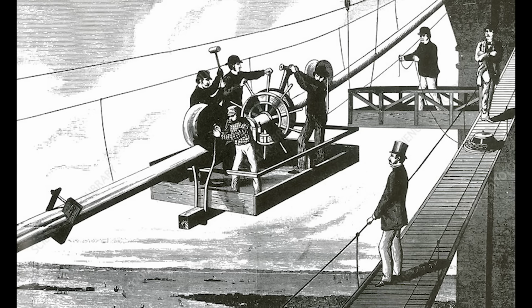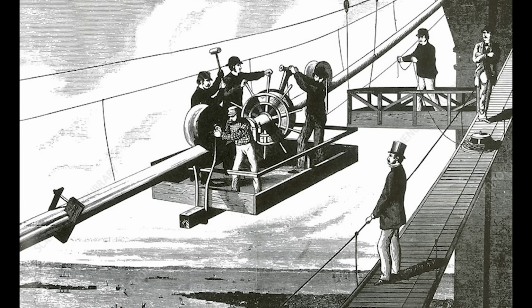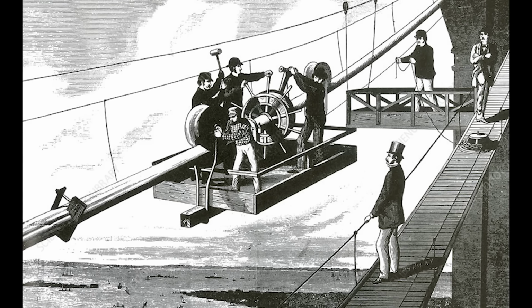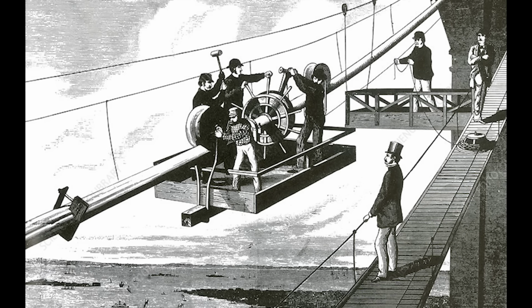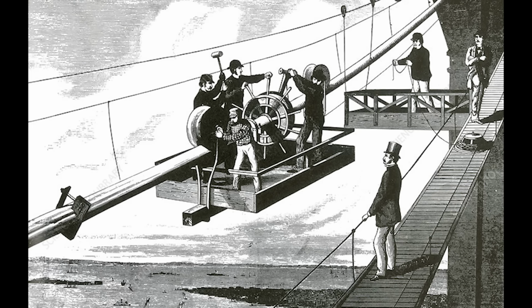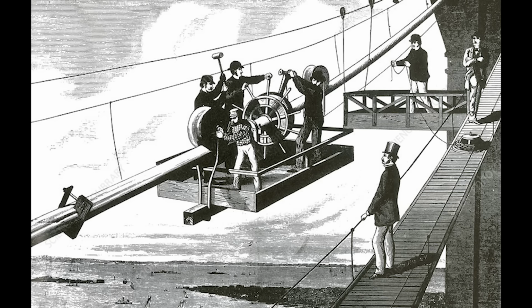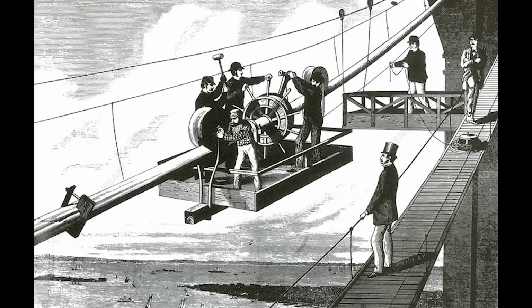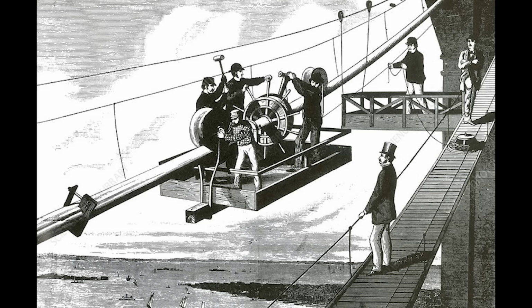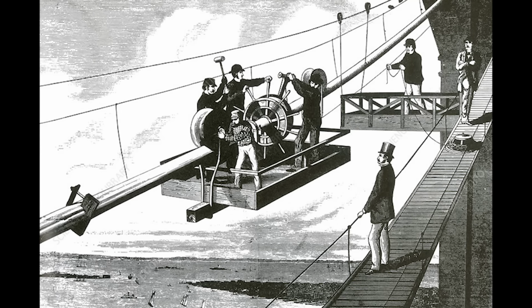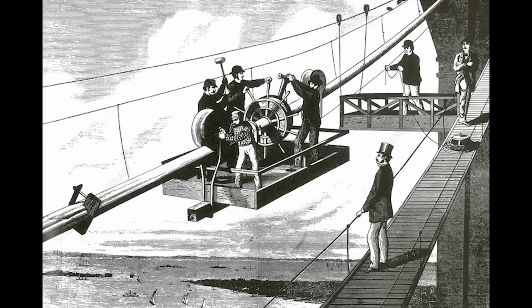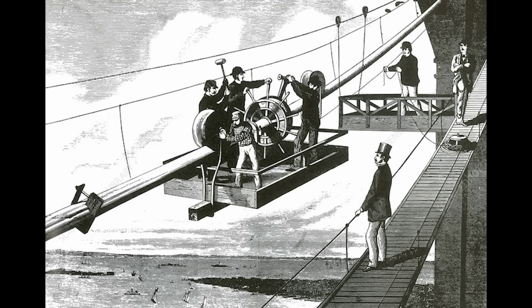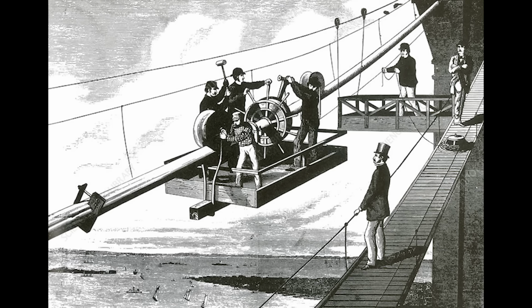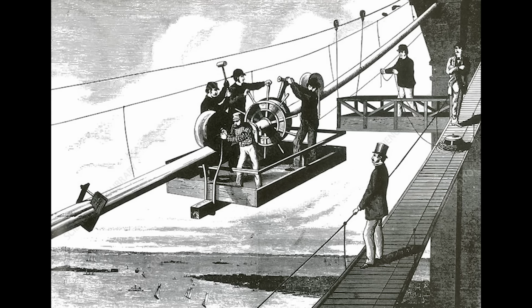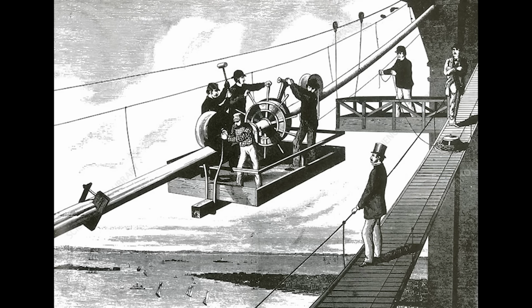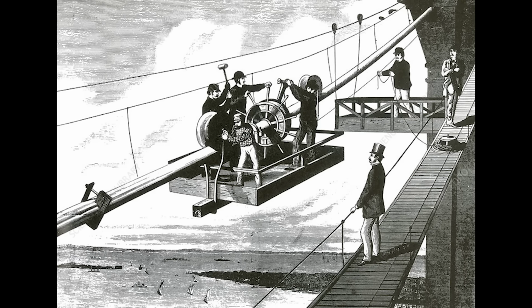The wire arrived at the Brooklyn yard in massive spools, each strand already bearing its zinc armor from the contractor's galvanizing works. Roebling examined the first delivery through his magnifying glass, noting the characteristic crystalline surface that indicated proper hot dip processing. The zinc hadn't been painted on or electroplated. It had been alloyed into the steel's surface through the molecular violence of molten metal meeting iron at 850 degrees. This was mechanism, not myth.